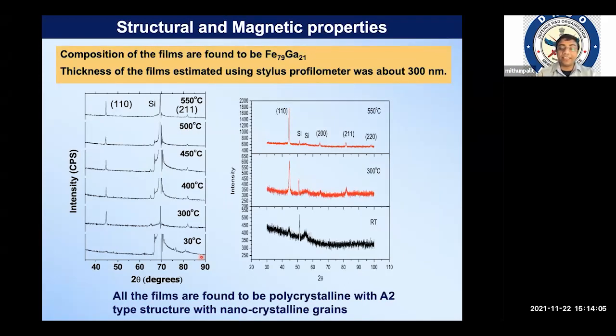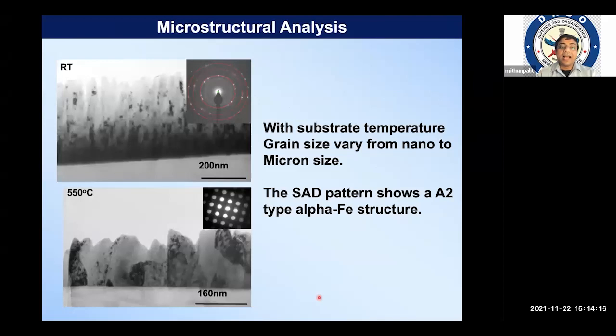And also we can see over here, this is the XRD. You can see that initially it was a very wide peak, and the peak sharpens as the temperature increases. Well, if you see the transmission micrograph, you can see that at the thinner sample, the room temperature sample, the very fine channels form, whereas at higher temperature, you can see this grain size, they're very coarse, the spots show over here, whereas very well formed bright spots form at the sample grown at higher temperature.